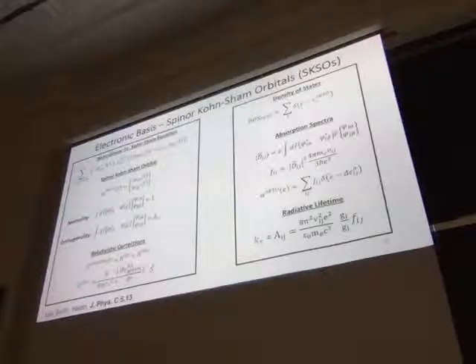Those are the orbitals, and these are the ground state observables we compute. We have the density of states, and we compute absorption spectra using the spinors. We compute a transition dipole between two orbitals, which feeds into oscillator strengths, and oscillator strengths are just the probability of photo-excitation between two states due to coupling to the electromagnetic wave. You can make an absorption spectrum from that, and from the oscillator strengths we can also compute a radiative lifetime using Einstein coefficients for spontaneous recombination. So that's a charge neutral model, with no polaron.